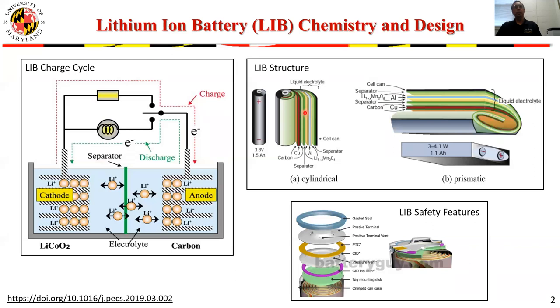So now let's talk a little bit about what makes them hazardous in principle. What is the reason for the underlying accidents that we briefly mentioned in the previous slides? Well, when you take these lithium ions out of the cathode, you create a chemical that is too rich in oxygen and is in principle unstable. That chemical can decompose with the production of oxygen, and that decomposition can actually be quite exothermic. So by charging the battery, you're creating an opportunity for new chemistry that is not part of the charge and discharge cycle.